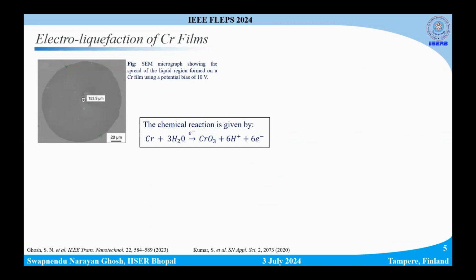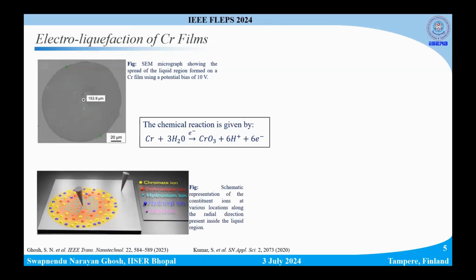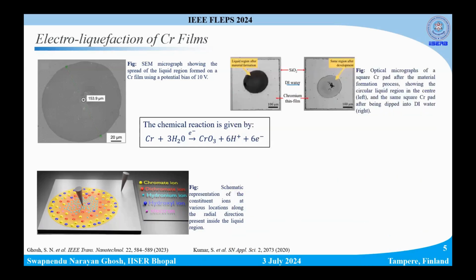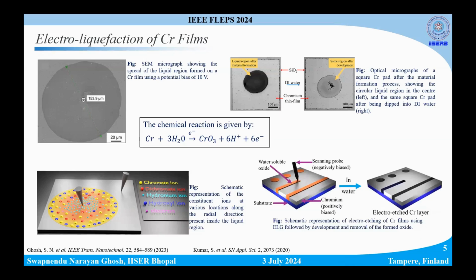The liquid material is a result of an electrochemical reaction that takes place, given by this chemical equation. In the hydrous domain, the chromium oxide stays as chromate and dichromate ions. Now, chromium trioxide is the only chromium oxide which has a high solubility in water. Therefore, once this oxide region is formed, if we dip the sample in water, we can effectively etch the chrome layers off. In all these cases, the cathode probe was kept fixed. What happens if we traverse the cathode probe according to our required design? We can obtain patterns on the chrome layer, and after dipping the sample in water, we can effectively electro-etch the chrome layer. And this is what has given rise to the scanning probe-based electrolithography technique.